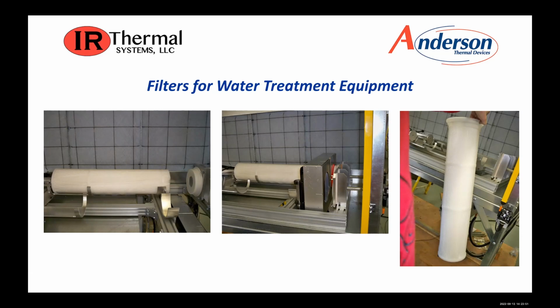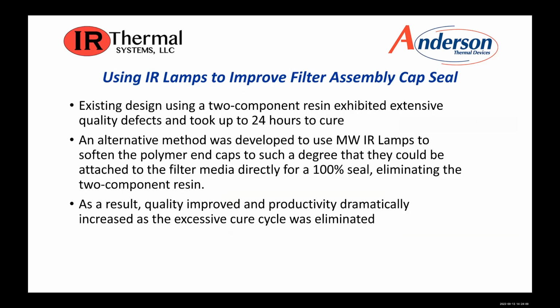In the past, before they were using any type of thermal welding, they would use, again, a two-component exothermic resin or epoxy to bond these two. And this could take up to 24 hours. It was done in an ambient environment. So they would have to put together a whole bunch of filters and then let them sit before they could pack them out and ship them, test them, pack them out and ship them.